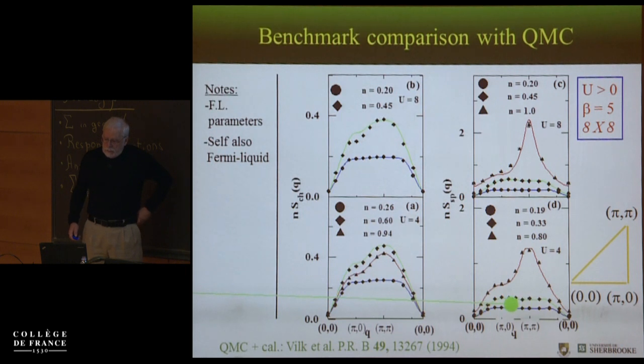And the TPSC calculations are the solid lines, and the Monte Carlo are the dots. So you see they really fall on each other, and it's not trivial, because if you look at the charge fluctuations, you see this is 26% filling, 60% filling, and 94%, so it goes up and down. It's not monotonic. And this you can assign to the Pauli principle. In other words, the spin fluctuations are going up, and the charge needs to go down to satisfy some rules.